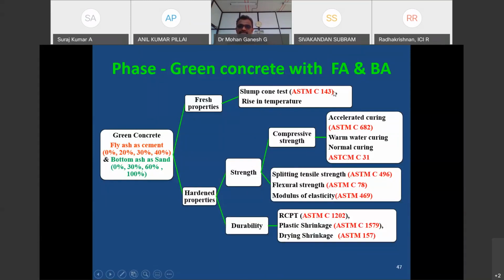The slump cone as per ASTM standard C143, and these are all the various hardened properties of the concrete we have done. Again, the hardened property we can classify into strength as well as durability aspect. The strength basically is compressive strength. So for finding the compressive strength, normal curing, then the accelerated curing, warm water curing, we have done it.